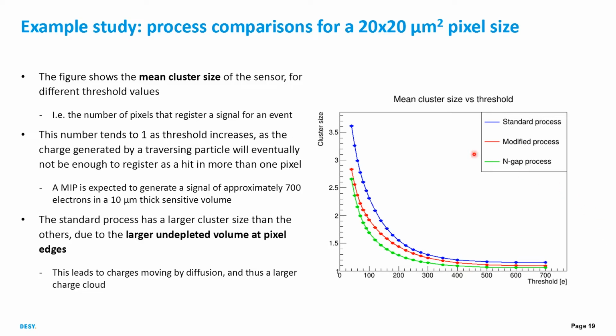But we can see that the standard process has a higher cluster size than the other two, and this is due to a larger undepleted volume at pixel edges, which means that charges at the pixel edges in the standard process move primarily by diffusion, and thus we get a larger charge cloud, which means it can spread to more pixels, and then we get a larger cluster size.